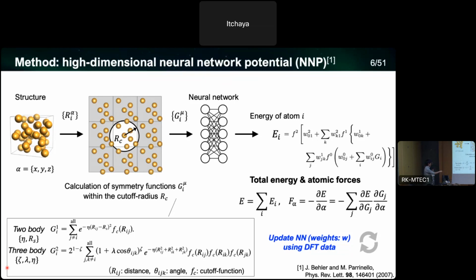The exact symmetry functions are like this. We are typically using two body terms as well as three body terms. In the two body terms, which are the summation of the Gaussian function, this Gaussian depends on the distance between the central atom and the surrounding atoms. Summing up all these Gaussian functions will give you one numerical value. And in the three body terms, in addition to the Gaussian part, we also have the angle part. So we can get different values by using these two and three body terms.